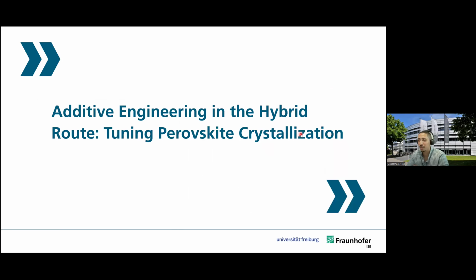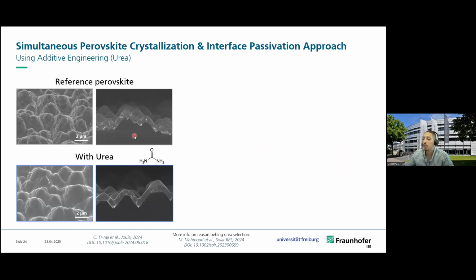So now we talked about a lot of issues and challenges. What about finding solutions? In order to reduce the mobile ion density that we talked about and improve the conversion, we turned our attention towards additive engineering to further tune the perovskite crystallization. In particular, we used a very strong Lewis base, which is urea, which can easily coordinate with lead iodide during the perovskite crystallization. As a result, we observed a large improvement in the apparent perovskite grain size. Also at the interface, where we had a lot of lead iodide, we started to see that it became much neater.